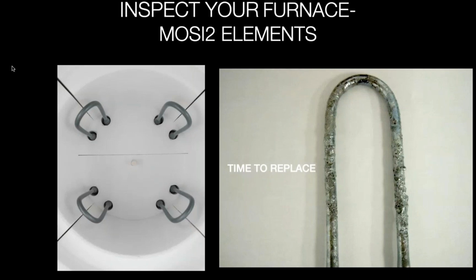And there's a beautiful booklet by a company in Germany, which I'll remember in a second, but they make the elements for the VITA furnaces, and they make the insulation, they make everything just for ceramic furnace applications. And they had a beautiful explanation, and they actually contaminated deliberately with all kinds of different elements to see what color they would produce, and you could see that none of them except the glass from the little chips of this silica were the offending ones that would cause the discoloration on some zirconia.